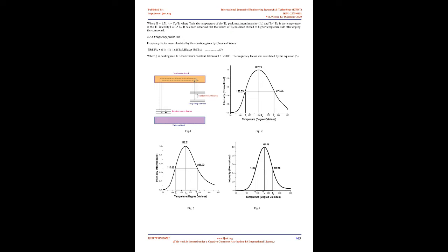Taking the same amount of sample, 5 mg, thermoluminescence, TL, emission spectra were recorded using a Nucleonics thermoluminescence reader, integrated PC-based, TL 1009I. 3. Results and discussion. 3.1 Analysis of trapping parameters. Fig. 1 shows the multi-level TL model for competing trapping and luminescence centers. The shallow traps get emptied earlier and the deep traps, acting as a reservoir, may replace them subsequently, or the carriers can also go directly to the conduction band and recombine with the luminescence centers during their back journey. Here, on the basis of the TL results, the trapping parameters were calculated by Chen's half-width method.